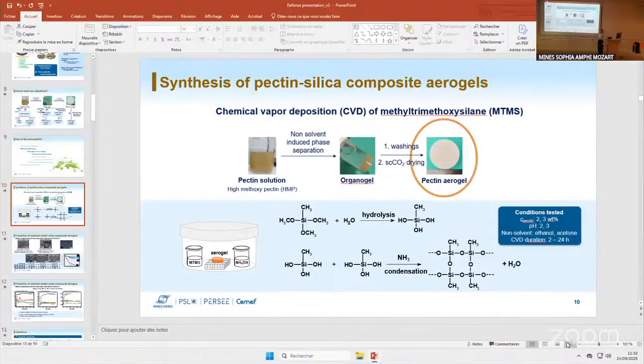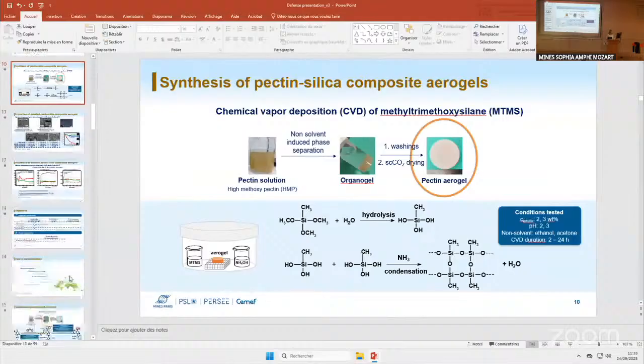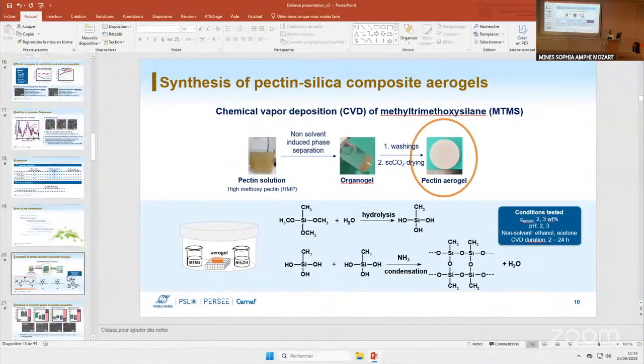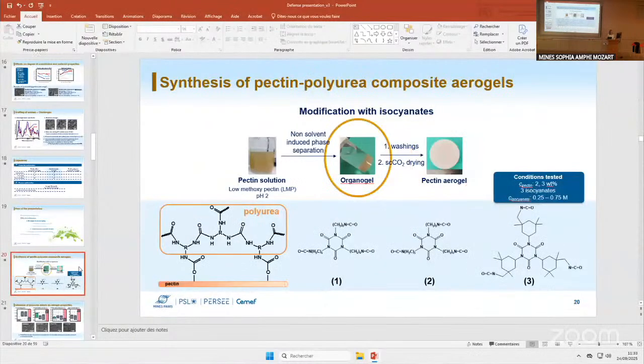Then I have quite some questions on the polyurea pectin composites. You show in the reaction mechanism that you can have both urethane bonds and urea bonds, from the water, like the urea makes the amine from the isocyanate. What for me was a bit missing, how much water was in your sample? We don't know exactly how much water we have. So we know that after solvent exchange, we have some water staying confined in the pores of pectin, but we have not identified the exact amount. It would be very low.